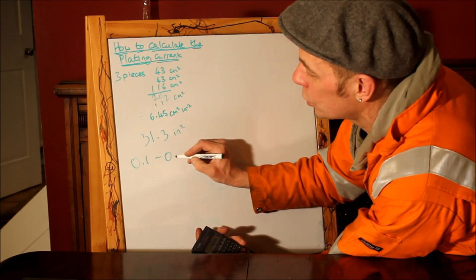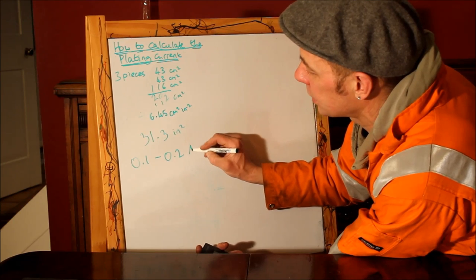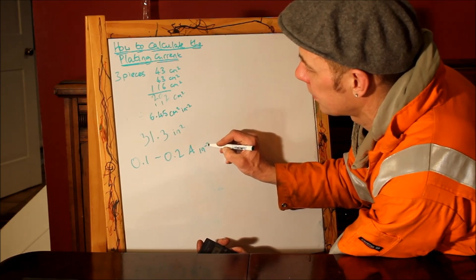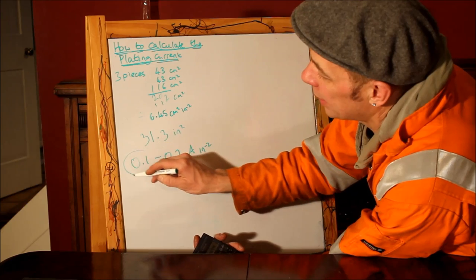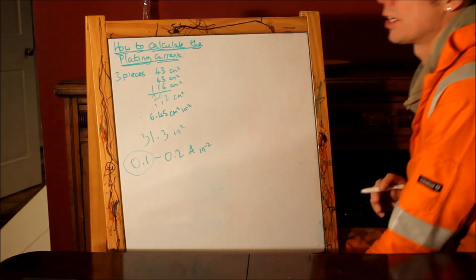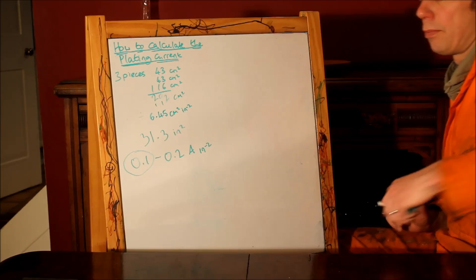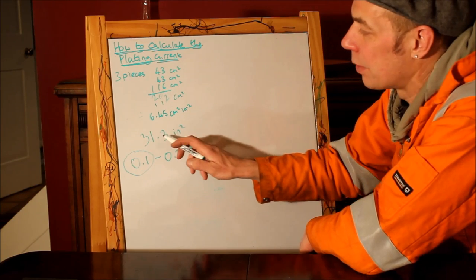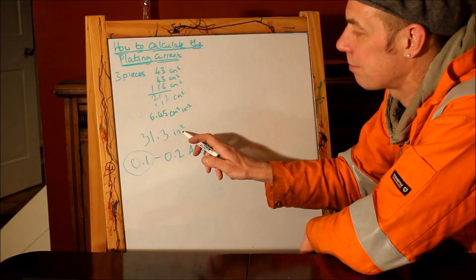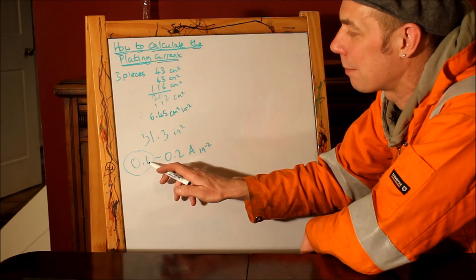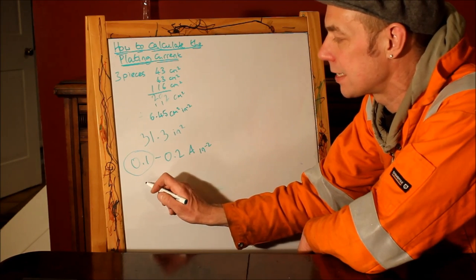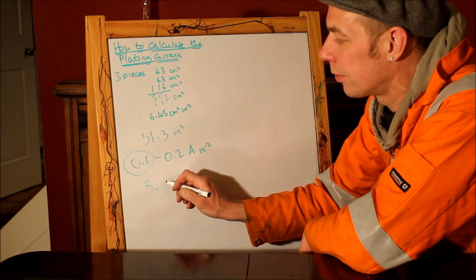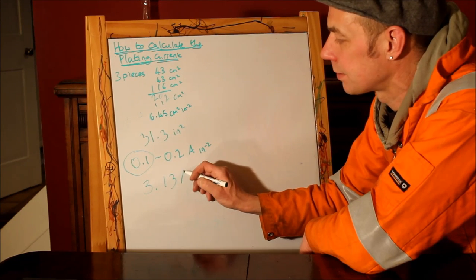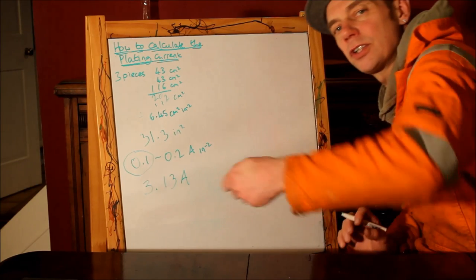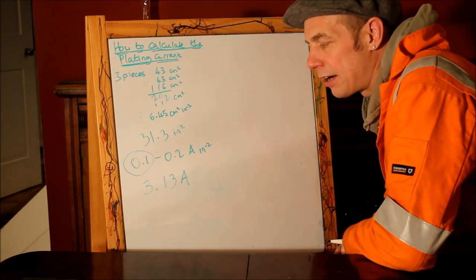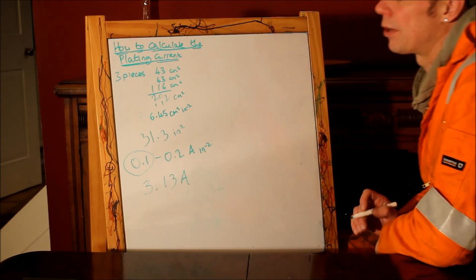Now you want to plate at between 0.1 and 0.2 amps per square inch. And I would recommend plating at the lower end of the range. So work on plating at 0.1 amps per square inch. So we've got 31.3 square inches of metal to plate, and we're going to do it at 0.1 amps per square inch. So that means that we need a plating current of 3.13 amps. Okay, so we're going to adjust the resistance on that variable resistor to get the current as close to 3.1 amps as we can.